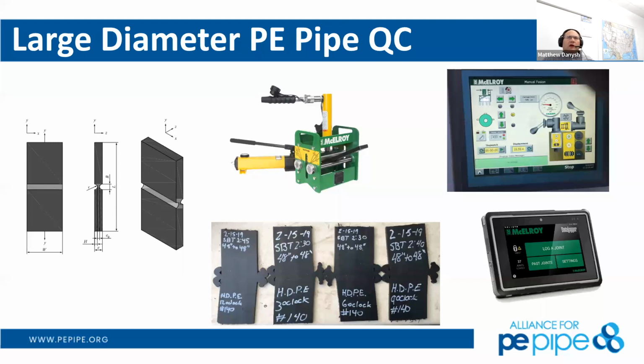And so we really encourage people to look at their welding procedures and parameters to ensure that we have good welds. And then we also can do different types of tests. The samples on the left are a constant tension load test where we can do tensile loads on the test to test for stress crack of the pipe. And then there's also the old method of doing weld tests with the bend back test method. And then you have the recording for a joint to ensure that you have good joints and weldability in the large diameter pipes. Yeah, so I think it's safe to say, Matt, if you're a new engineer designing HDPE for the first time, there's lots of different test methods for the production, the resin, the pipe, producing the pipe, tensile impact tests.